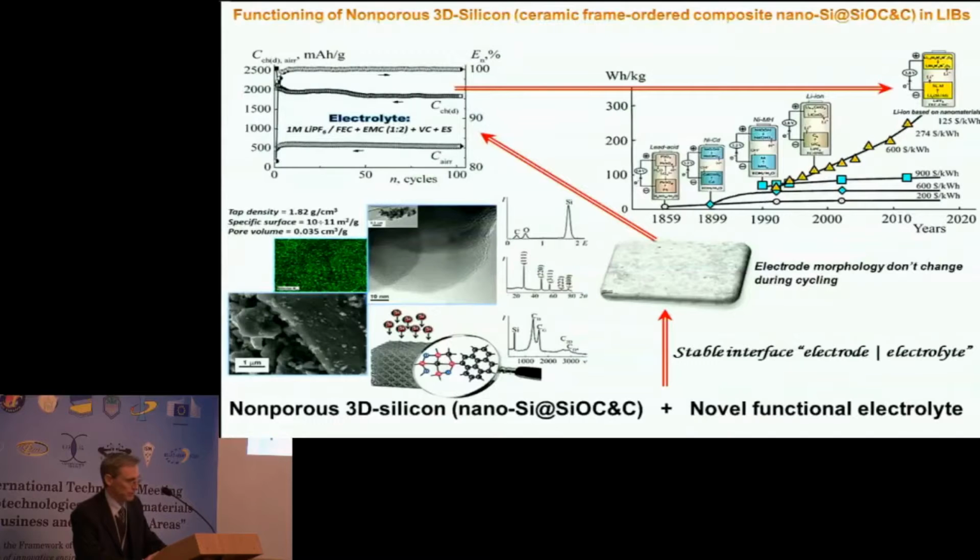Ethylene carbonate was totally replaced by fluoroethylene carbonate. A new composition of a aprotic electrolyte was proposed with the introduction of 2, rather than the traditional 1, functional additives. Such a composition of electrolyte dramatically improved the cycling parameters of alloying electrodes. After the appearance of our applications in 2010 devoted to the effectiveness of electrolytes based on fluoroethylene carbonate, a complete replacement of ethylene carbonate with fluoroethylene carbonate, the necessity for fluorocarbonate on the market has increased dramatically.